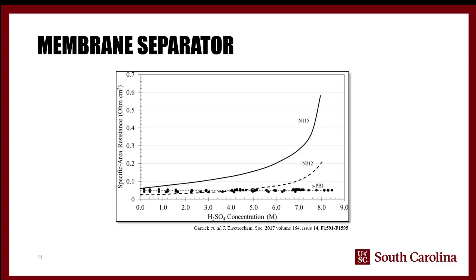But as you can see with Nafion, as you get to about 6 molar, with even a thicker membrane here, you start to see this exponential increase. Similarly for the 115, it's a huge increase, and you're getting up to easily an order of magnitude higher resistance. And of course that means that you have added voltage loss, and so to achieve the same current density, you've got to apply more potential. And so this SPBI membrane is one of the other big steps that we're taking.